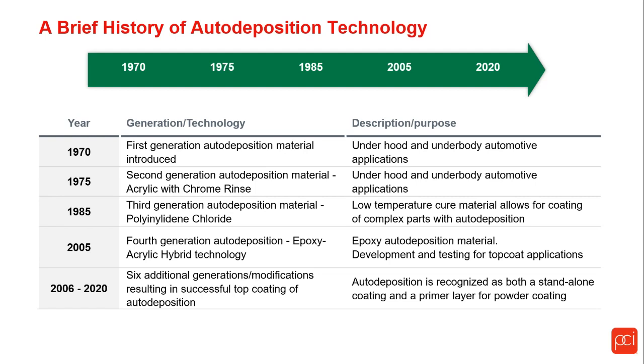Then in 85, the third generation came out, and this was a whole different product here called PVDC. Had a low temp cure and really allowed for complex parts to be processed through it because of the low cure temperature. Once again, though, staying with the underhood, underbody application. And then in 2005, the fourth generation came out, and this was the epoxy acrylic hybrid.